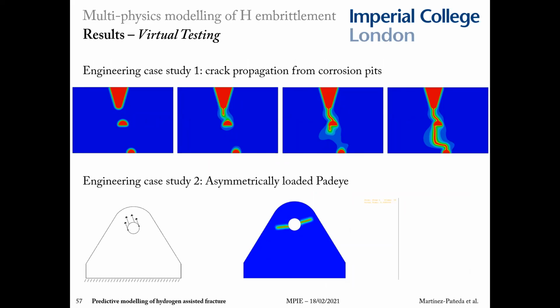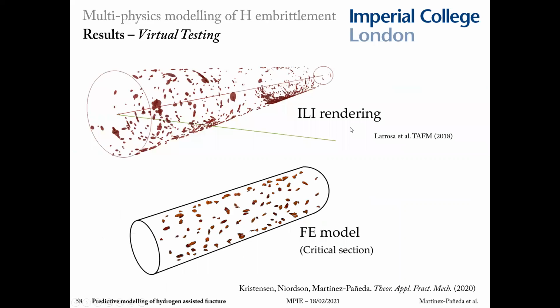And these are a couple of toy examples. The first one deals with a crack propagating from existing pits due to corrosion. And the second example simulates crack propagation in lifting equipment made of a high-strength steel. But more excitingly, we can model large-scale 3D problems and correlate our models with inspections, creating a digital twin of critical infrastructure. Here you can see a pipeline containing multiple defects due to pitting corrosion that has been characterized by Larrosa and co-workers using non-destructive evaluation.